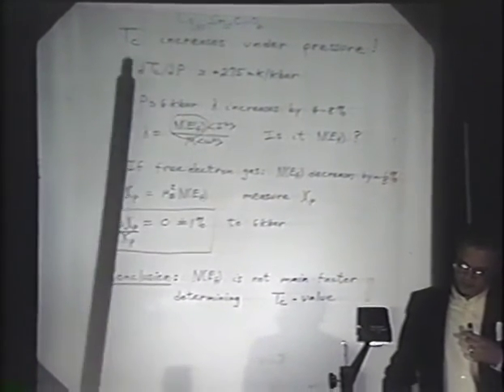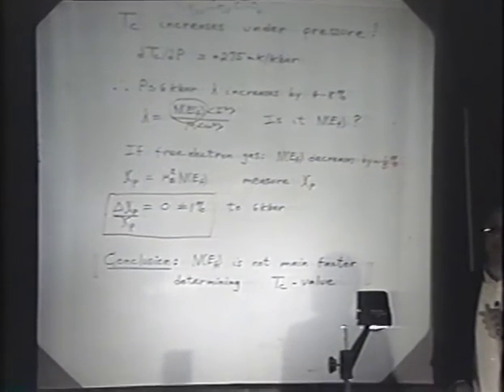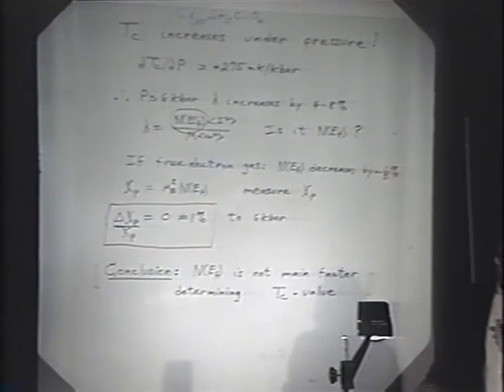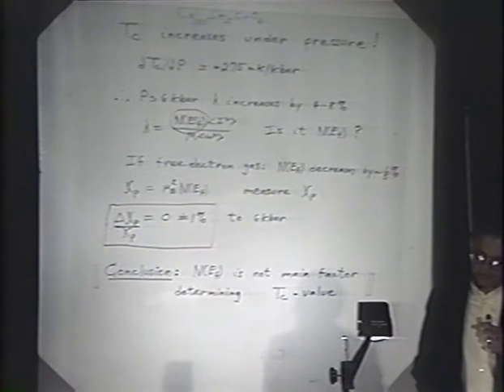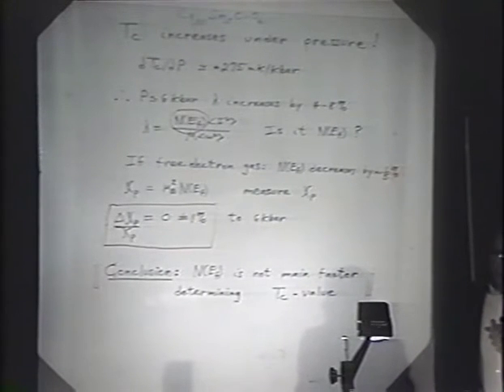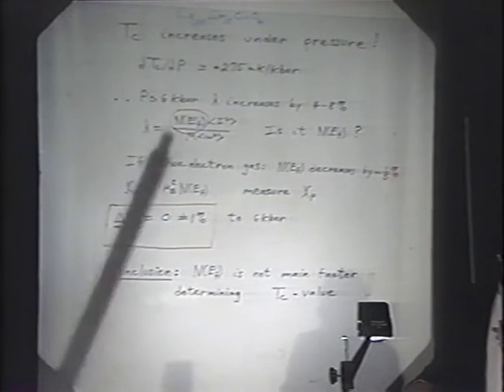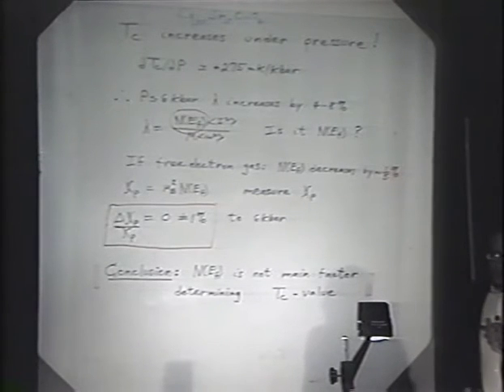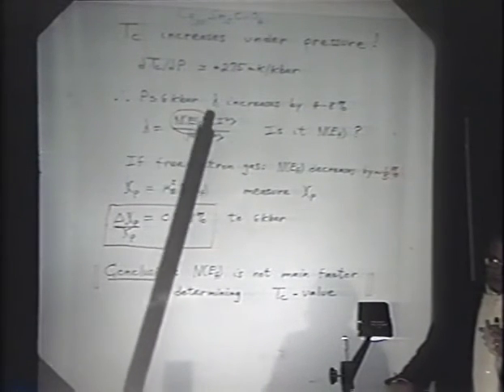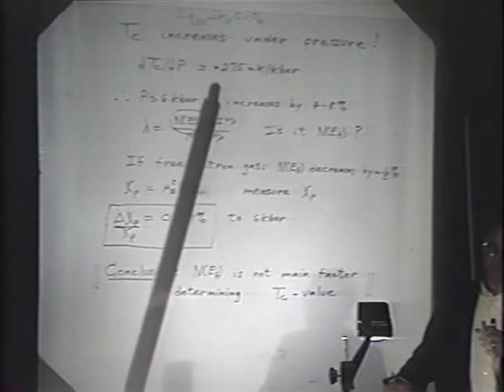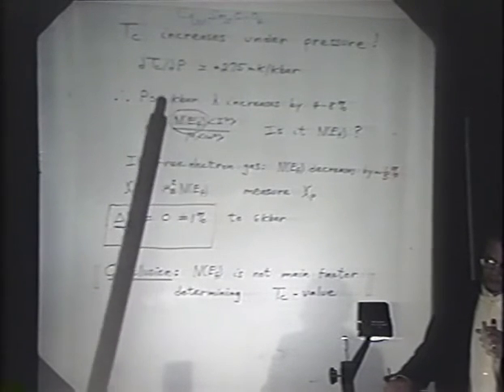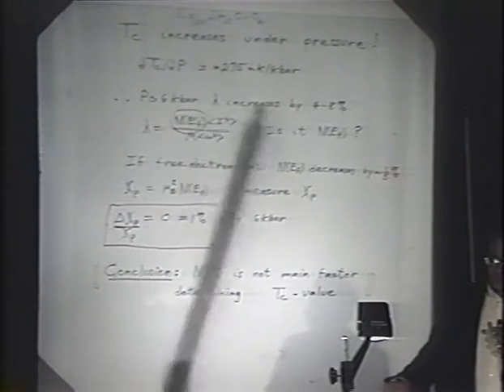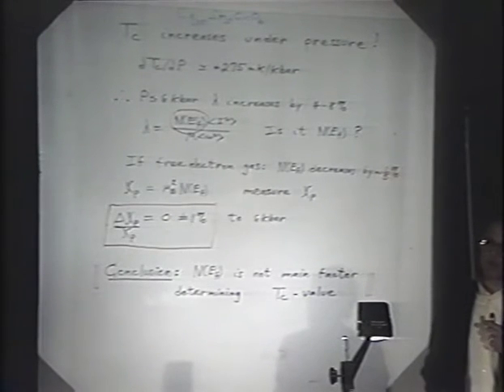Lanthanum strontium's TC value also increases rather rapidly under pressure, approximately 280 millikelvin per kilobar. This is a value similar to that found by the Karlsruhe group and also in Ames. Now, the question would be, why does TC go up so fast? The lambda value increase that you need, if you use a McMillan formula, to account for this increase that you get at 6 kilobars, so about 1.5 degrees, would be an increase of approximately 4 to 8%.